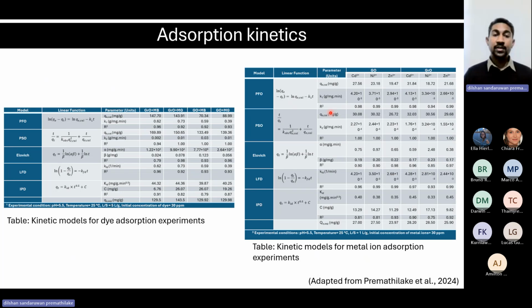I tried 5 different kinetic models in order to get more details about the adsorption process. With a high coefficient of correlation, you can see that both the metal ion adsorption and the dye adsorption follow the pseudo second order adsorption process. Here the coefficient of correlation is really high. However, the other models also provide lots of information about this adsorption, which is going to be very helpful in defining the adsorption mechanisms.